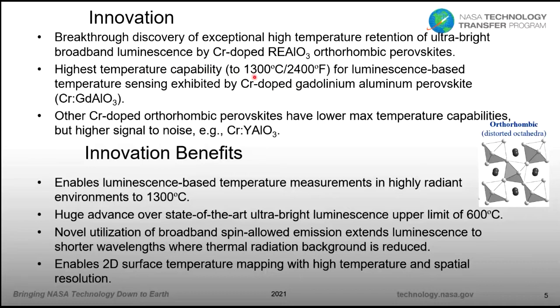That's 2400 degrees F. Although that gets you to the highest temperature, some of the other aluminates, although they don't get up to that temperature, can have higher emission strength at lower temperature for better signal to noise, for example, chromium-doped yttrium aluminate. So you might want to choose another aluminate if you're not trying to get to such a high temperature.